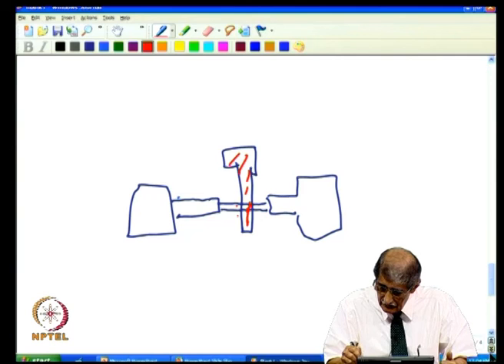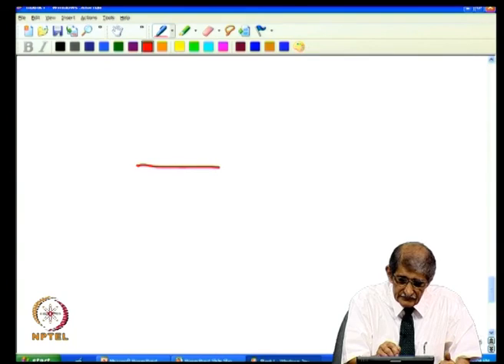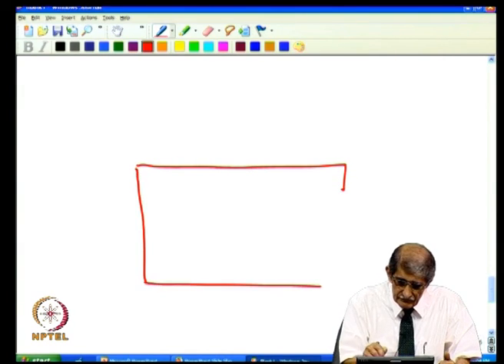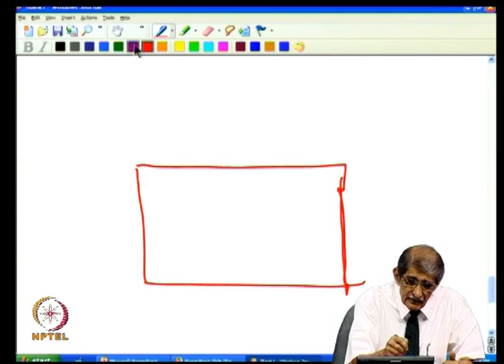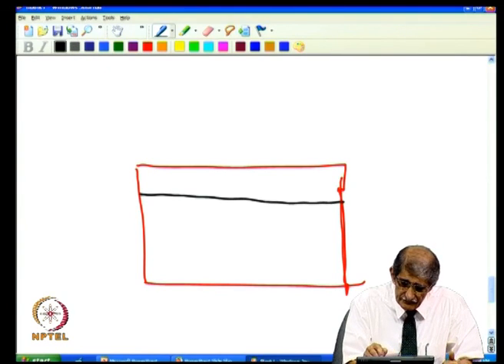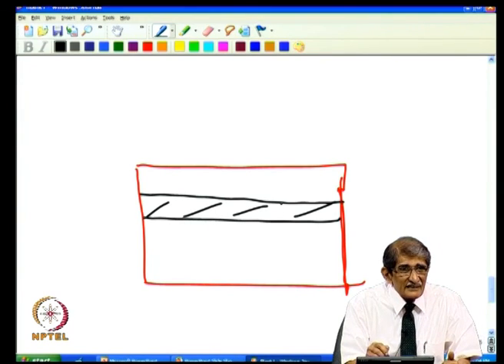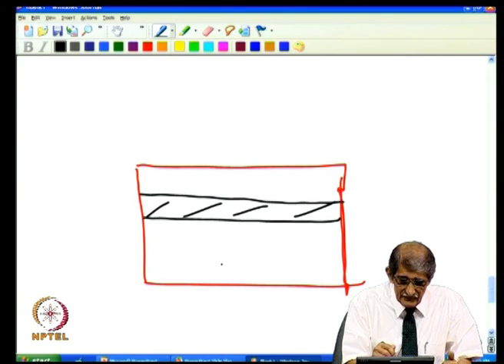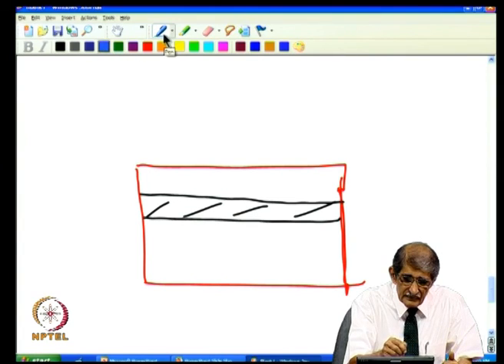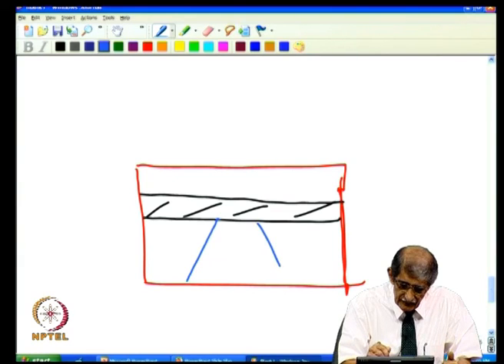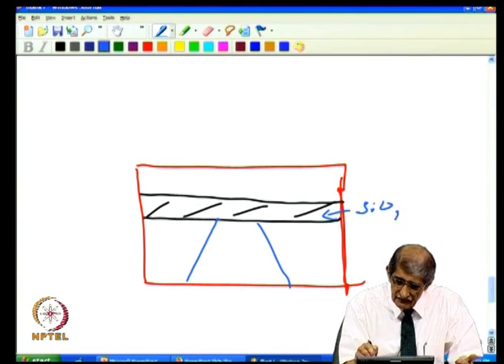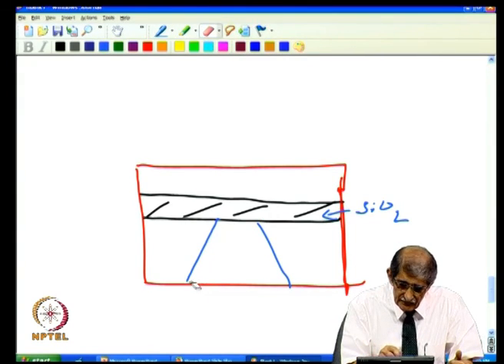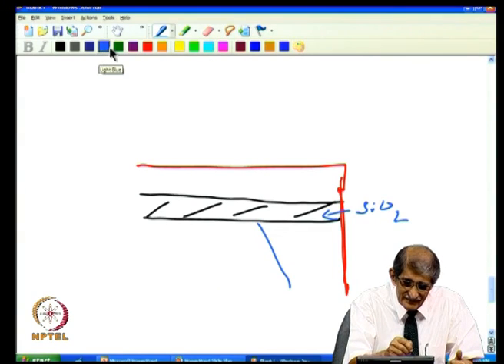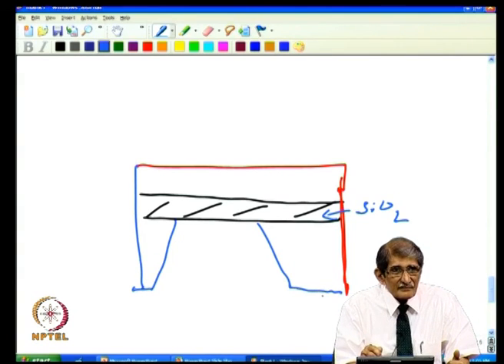For example, I can use an SOI layer, that is, there is a silicon, and I have an oxide here. That is SOI. I can etch silicon from the backside, either like this or vertically. With wet chemical etching it will go like that; vertically I can also etch. This is SiO2. After etching, you will have this gone, and you get it like that. I can etch the whole thing like this.